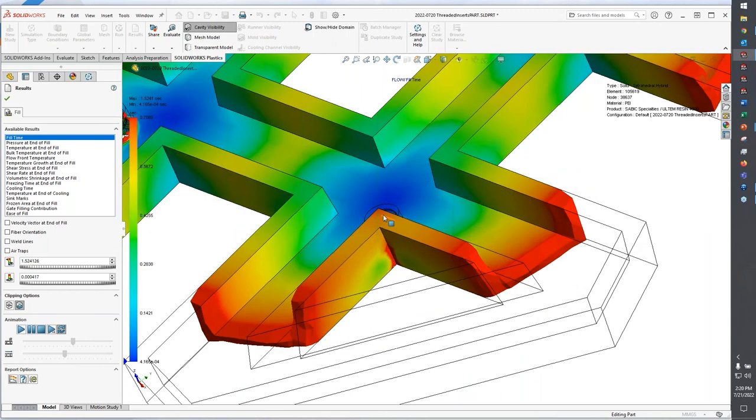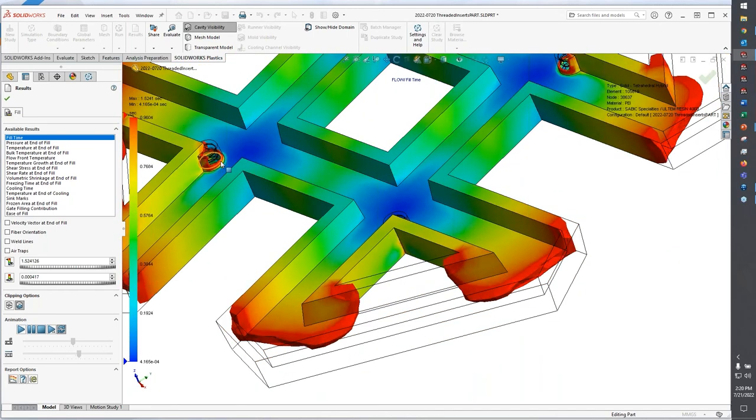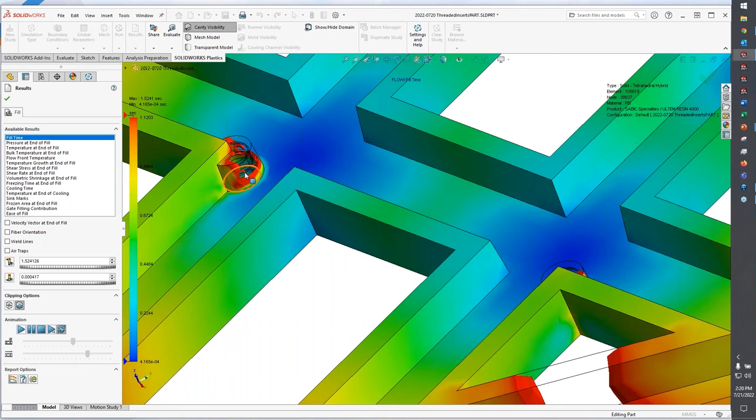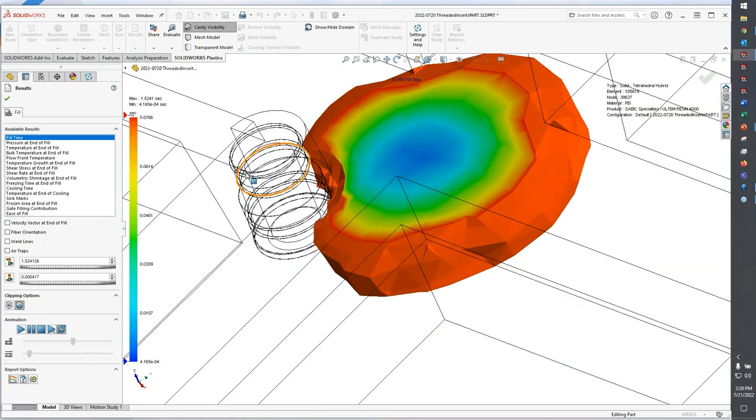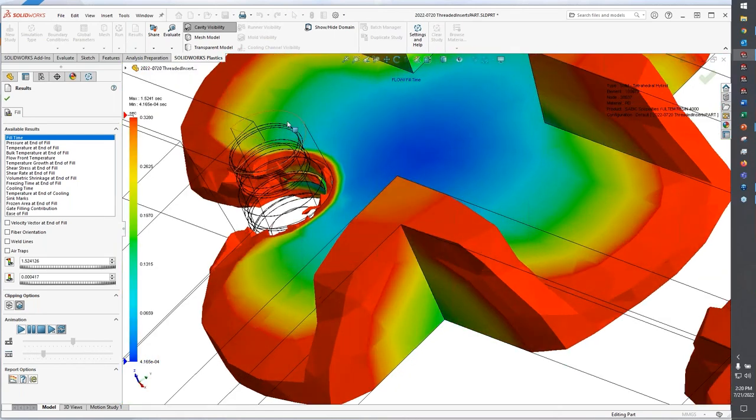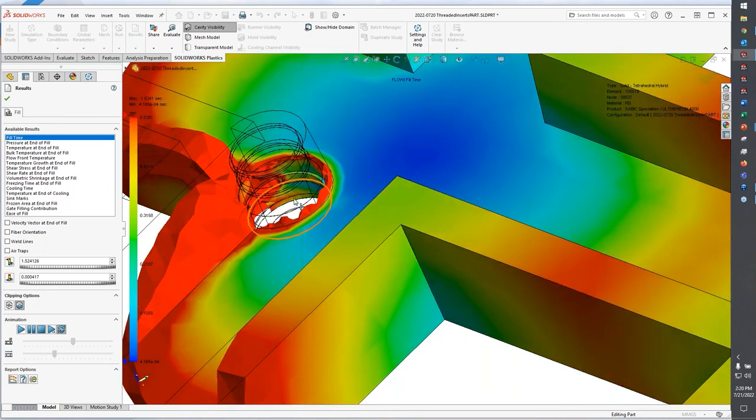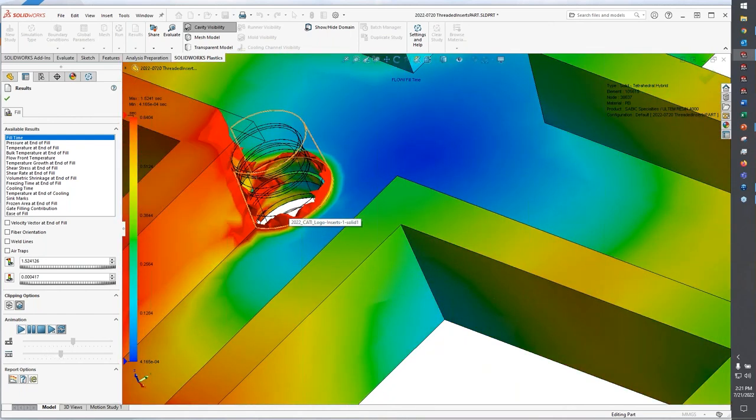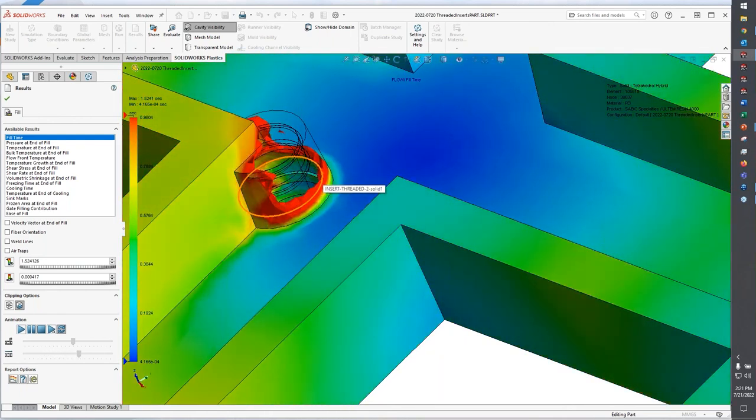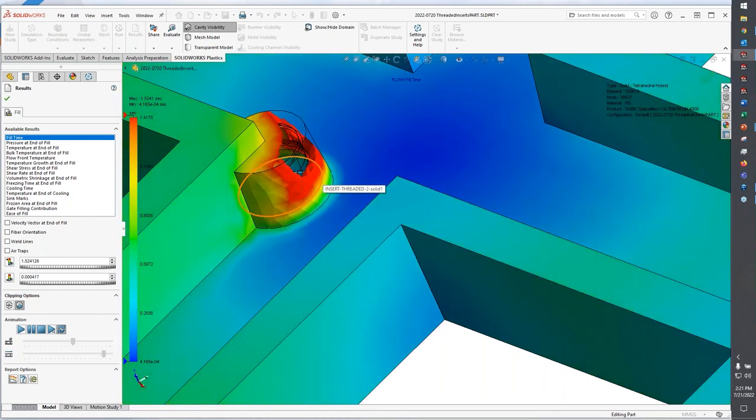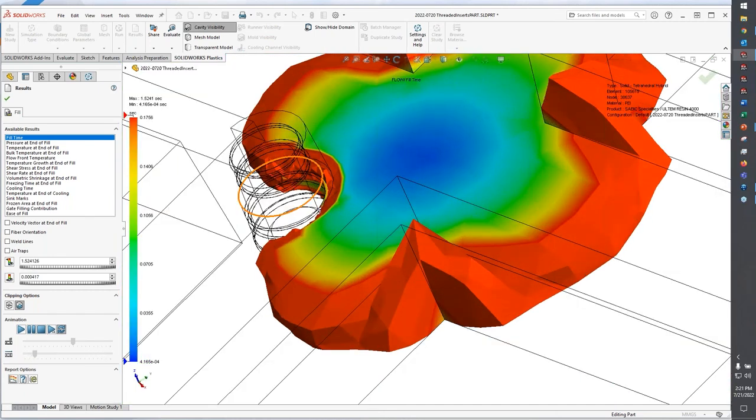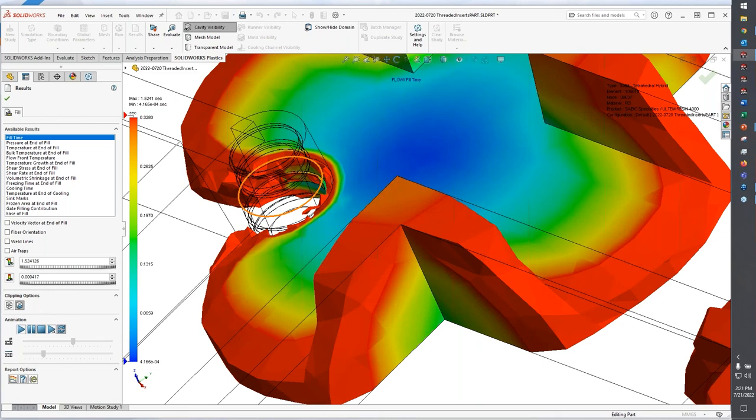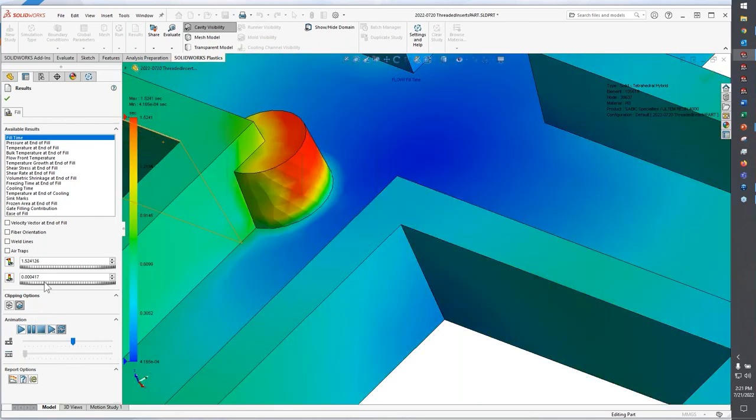I mentioned those inserts are going to be a lot colder, or if I didn't, the inserts are generally a lot colder than what your mold temperature is. So you're going to want to pay attention to how the melt front actually flows and fills around that insert, because as soon as that plastic resin hits that relatively cold insert compared to the mold walls, it's going to solidify very quickly.